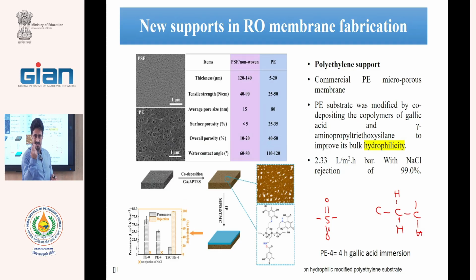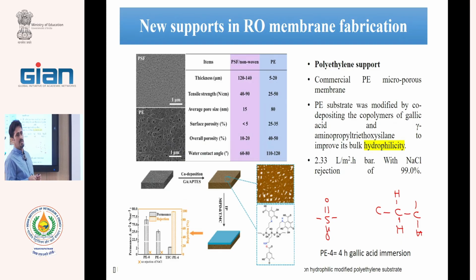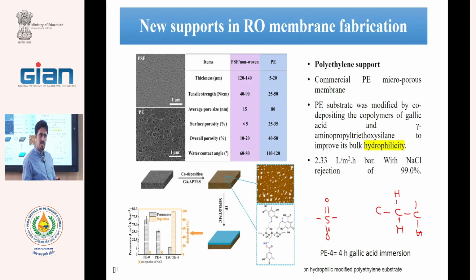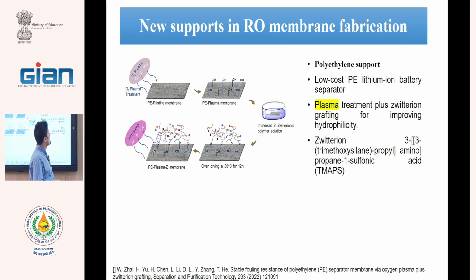And only 10 seconds of contact of plasma with polyethylene reduces the contact angle from 120 to 50. 10 seconds. Therefore, we usually use cold plasma, and the polyethylene layer goes through this chamber that has plasma, and during 10 seconds, the polyethylene can become hydrophilic and can be used in fabrication of TFC membranes, forward osmosis, RO, and others. In this slide, you see that oxygen plasma is used to make it hydrophilic and used for the coating of any reactant.